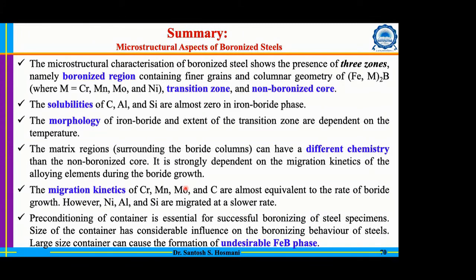Okay, so from a summary point of view, the microstructure. The boronized region consists of the iron boride, and this iron boride consists of not only iron, but also the elements which have some solubility there, like chromium, manganese, moly, nickel. That means we have some kind of mixed boride forming there. And in that particular boride region, you can have fine grains at the surface and columnar grains. Then it is subsequently followed by a transition zone. The transition zone consists of very tiny boride particles, and then subsequently the non-boronized core.